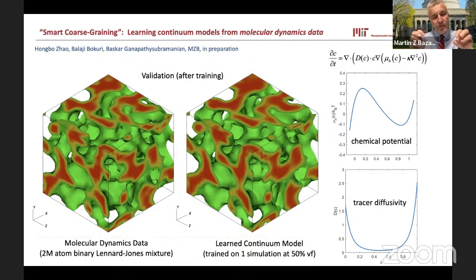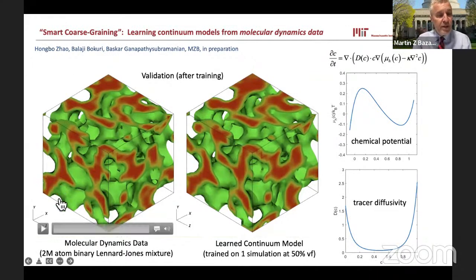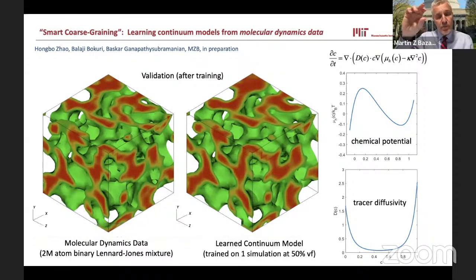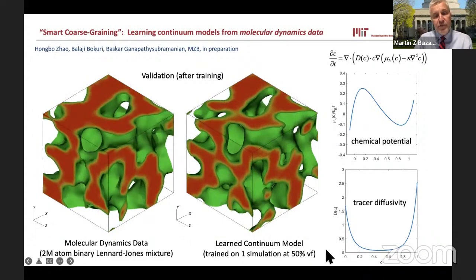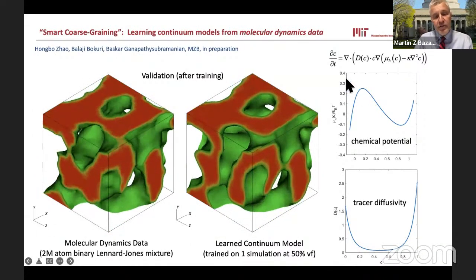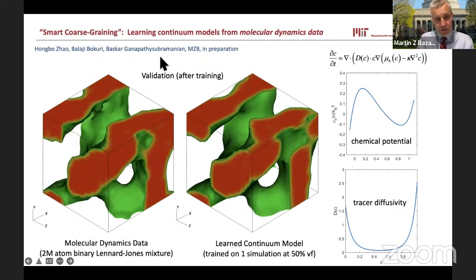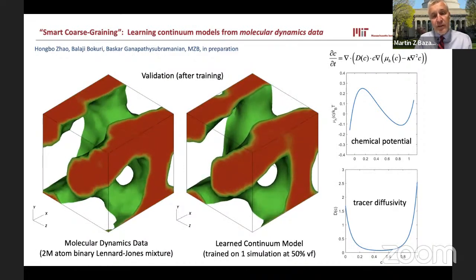And the interactions are set up so that the A and B are repelled from each other, but the same types are attracted to each other. So if you start with a mixture, then slowly the atoms fluctuate and they phase separate, very much like I showed you with the continuum model already. Now, if you take your 3D simulation on the left and you break it into voxels or cubes that are a little bit bigger than several atoms across, then you get this simulation on the left. But if I apply the methods I just showed you on the right, we can learn a continuum model, which is essentially indistinguishable from the molecular simulation on the left that's been coarse-grained at that sort of molecular scale, actually.